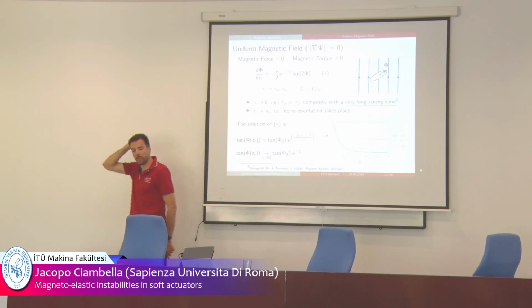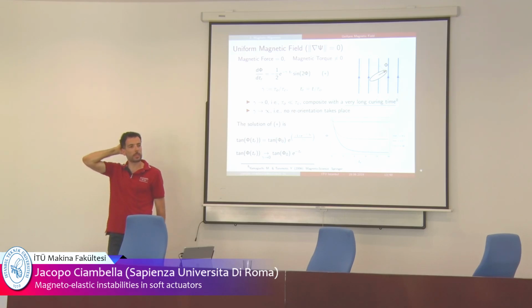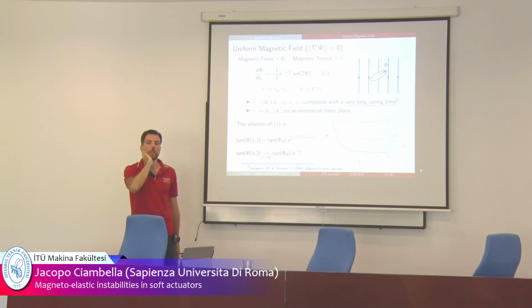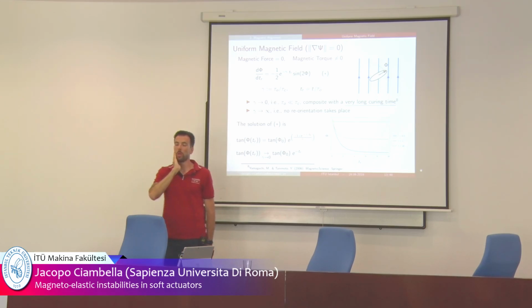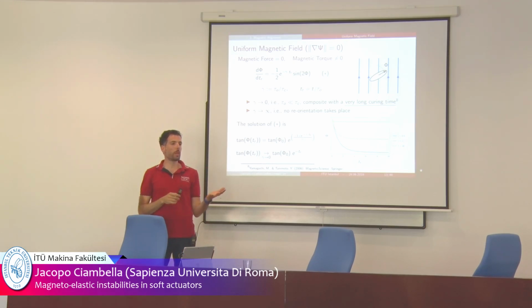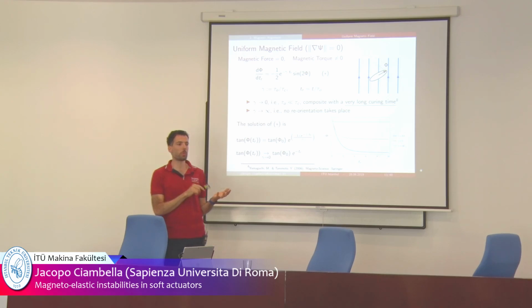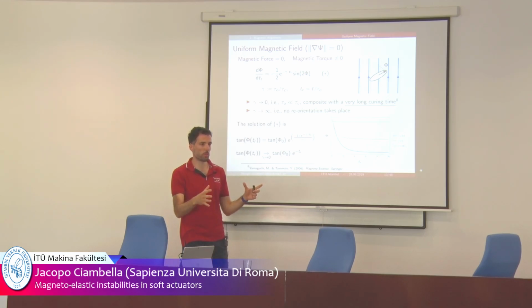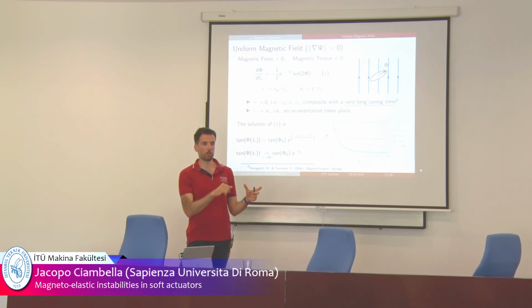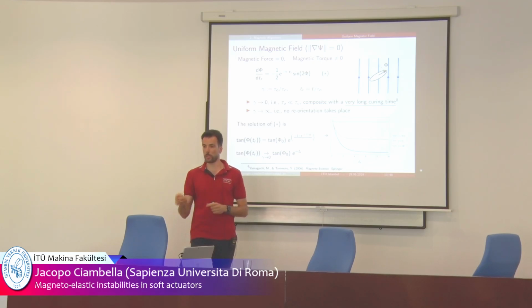What happens when the field is uniform? As I said, this is quite a peculiar situation, but it's very interesting from the experimental point of view. Why so? Because when you make your composite, you would like to have a homogeneous structure. So you would like to have particles which are uniformly distributed, and control only the orientation. So homogeneous material, but anisotropic.